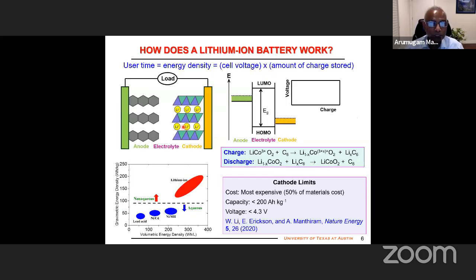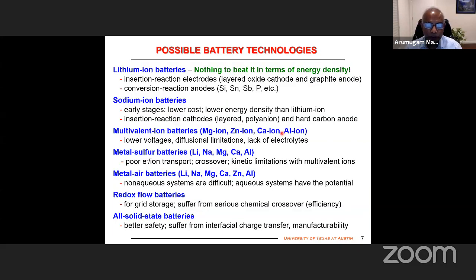see, during this process, these ions are also moving in this crystal lattice. If you have zinc ion or magnesium ion or aluminum 3+ ion moving, there will be a lot of electrostatic repulsion between the positive ions present in these materials and the working moving ion, zinc 2+ or aluminum 3+. So diffusion is going to become a big problem. So at the end of the day, even though it's very nice that I can store more charge, the diffusion becomes a problem, voltage will go down.